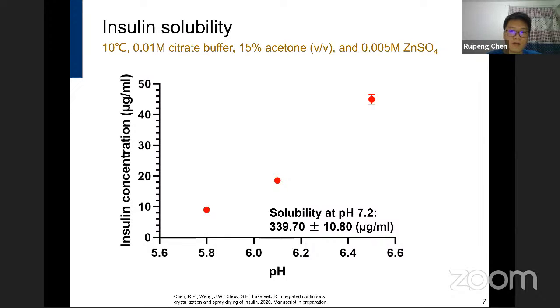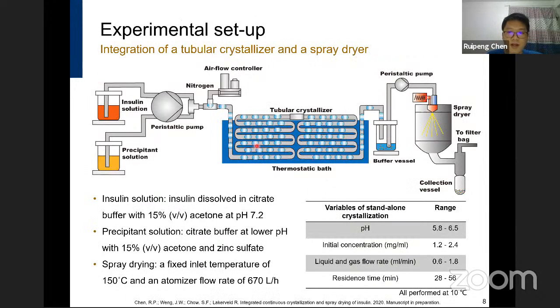So now is the experimental setup. Basically it consists of a tubular reactor and a spray dryer. For the tubular reactor, there are two phase solutions. One is the insulin solution, in which insulin is dissolved in the citrate buffer with acetone at higher pH by heating at 50 degrees C for 10 minutes and then cooled to room temperature. For the precipitant solution, it was citrate buffer at lower pH with acetone and zinc sulfate, because zinc is the essential component of the insulin crystals.